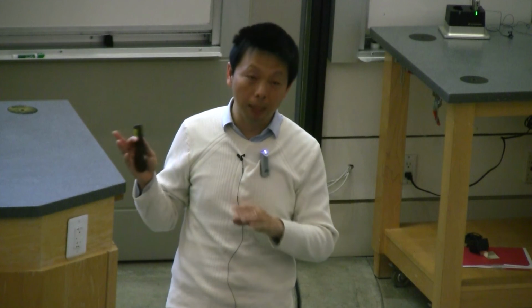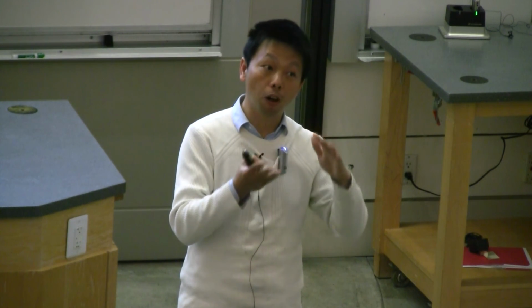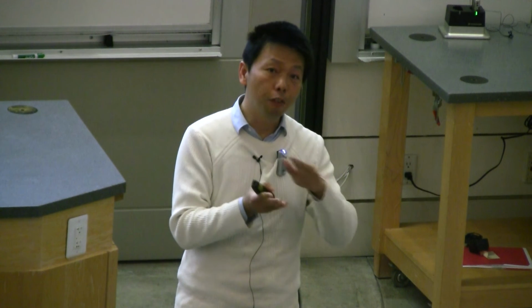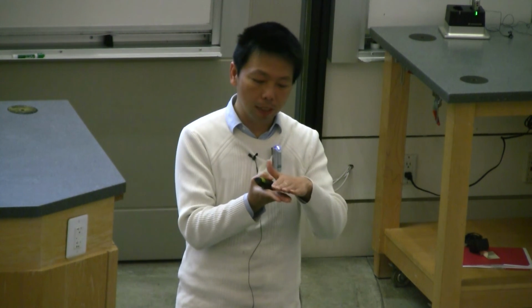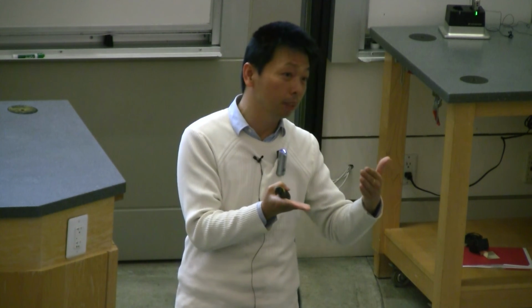So I guess my question was, is there a difference between these excitons and if you had an excitonic superfluid formed by tungsten diselenide, molybdenum diselenide in contact? Oh, okay. Yeah. That's right. So the main difference is that with HBN, the lifetime is much longer, although the exciton binding energy is reduced. If you don't have HBN in between, then the lifetime of the electrons and holes is only, say, tens of nanoseconds. So there's a serious question whether they will be able to thermalize effectively.